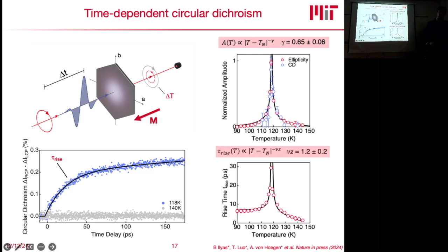But what we find is that you displace a phonon mode, and this phonon mode is strongly coupled to the magnetization, and it creates a magnetization. This is kind of a runaway effect, because the magnetization then leads to another distortion of the mode. So this is self-amplifying in this case. And the timescales are dictated by the timescales of the antiferromagnetic order parameter, which shows a critical slowing down, or a divergence in its timescales close to the critical temperature.